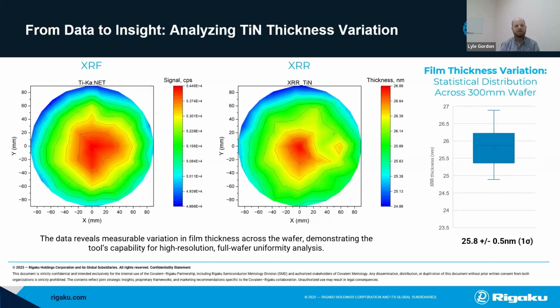So like what Max showed, we can actually get insight into the variation by mapping using a small beam across many points on the wafer. In this case, you can see, as we expect, a really nice correlation between the XRF data, which here is qualitative since we don't have calibration standards, and then the quantitative XRR. And you can see that the wafer actually, this is quite a uniform coating.